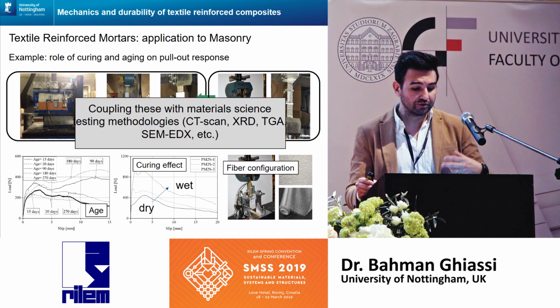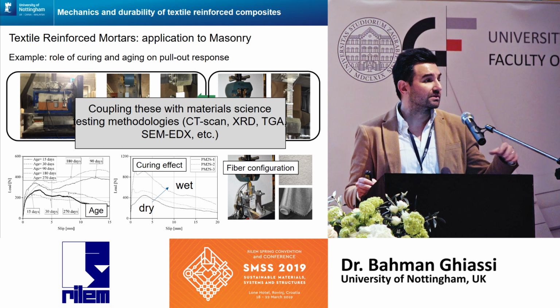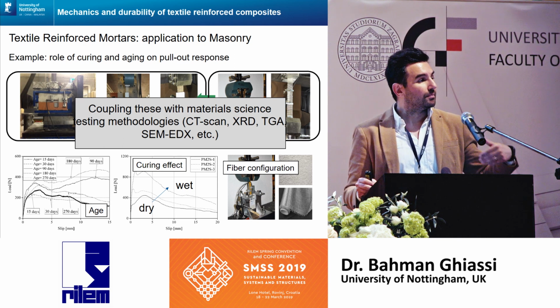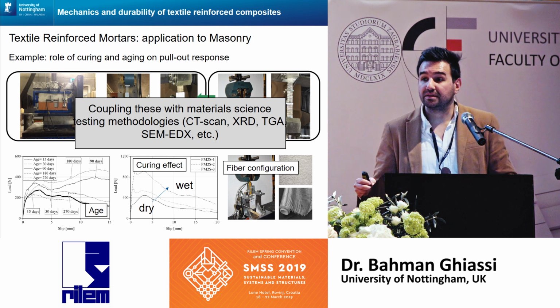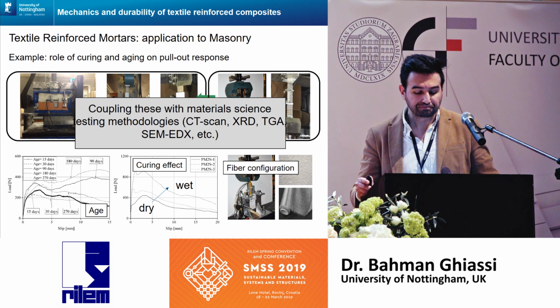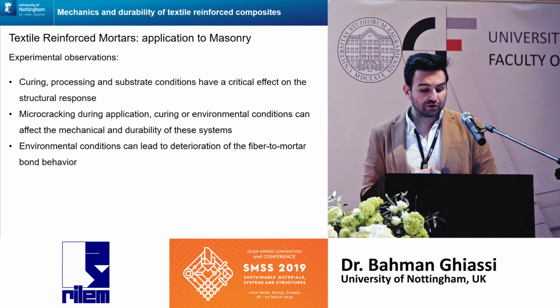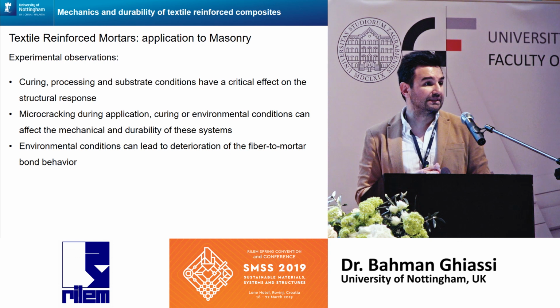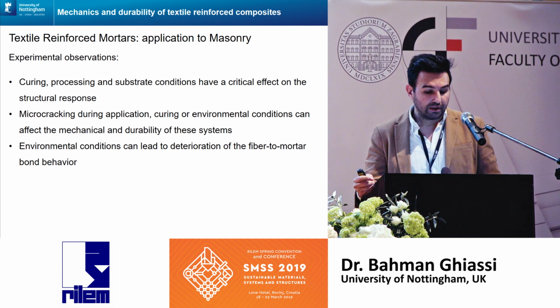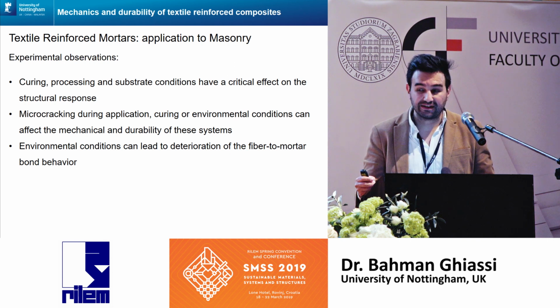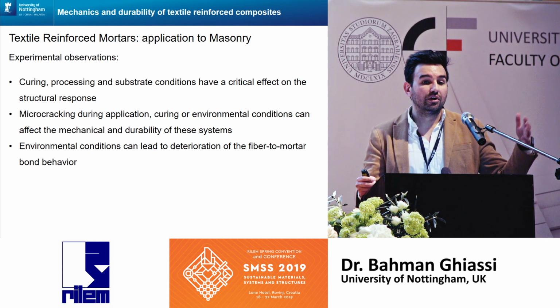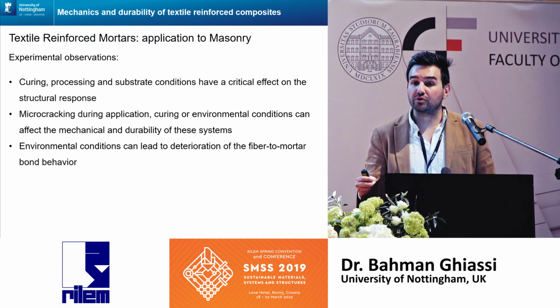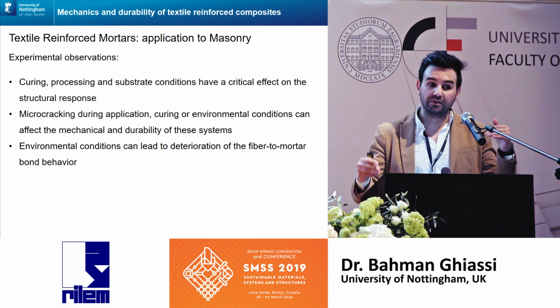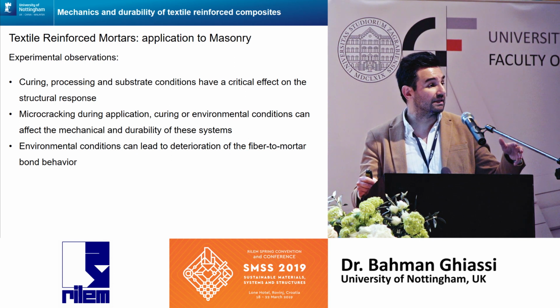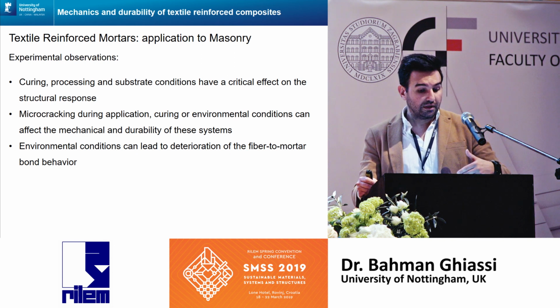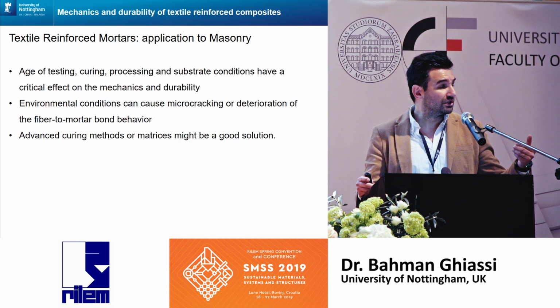And then at the moment we are trying to couple these results with material science experimental testing so that we can better explain the reasons for these changes that we observe. So just a short overview of what we have been seeing. We have been seeing that curing conditions, processing and substrate conditions can have a critical effect at various scales on the performance of these composite materials. And microcracking and deterioration of the interface between the fiber and mortar are the most common deterioration mechanisms that can happen because of these issues and also under different environmental conditions.